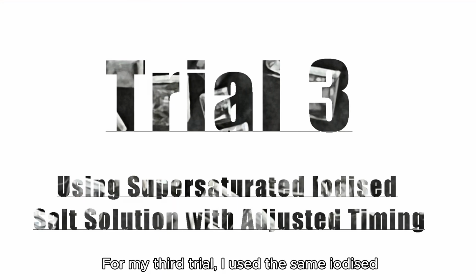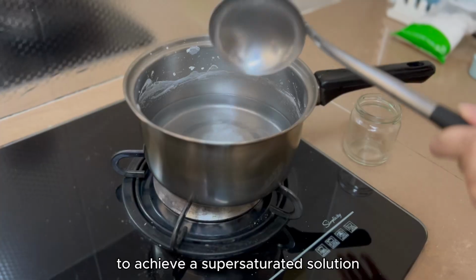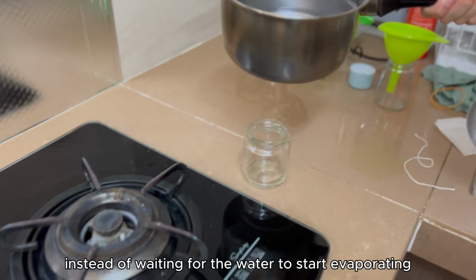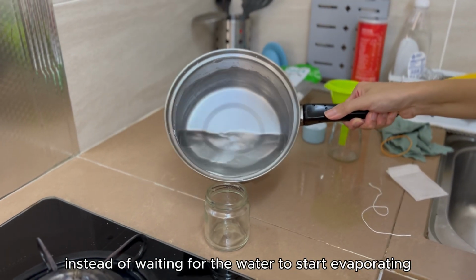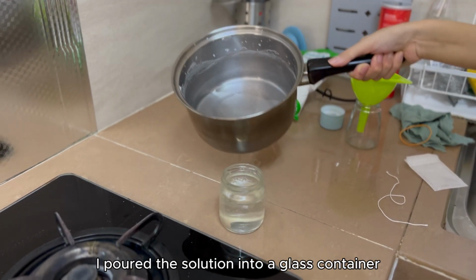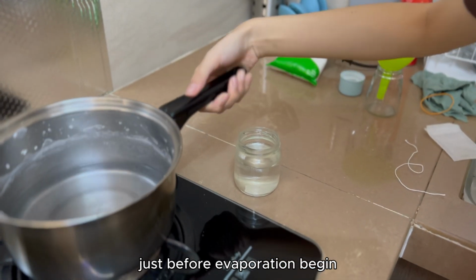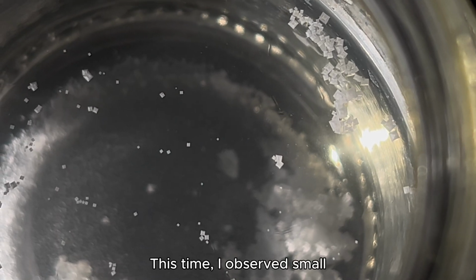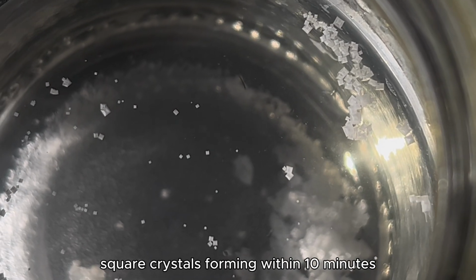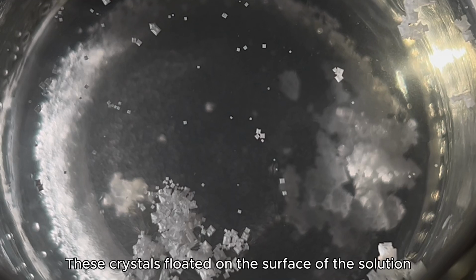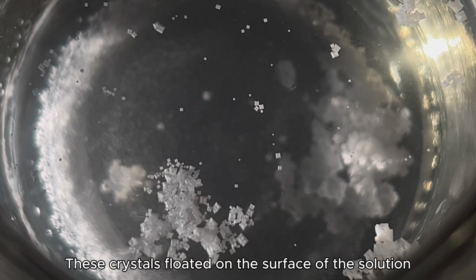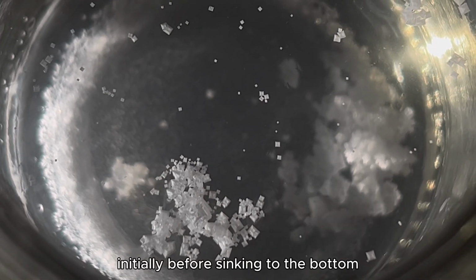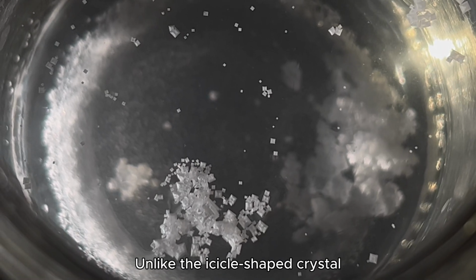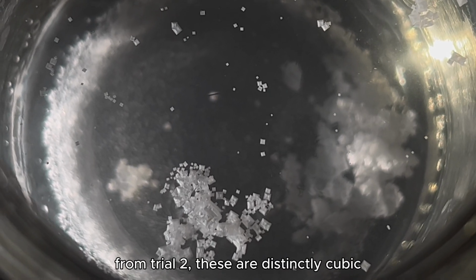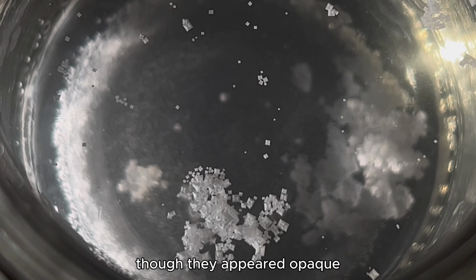For my third trial, I used the same iodized salt and heating process to achieve a supersaturated solution. However, instead of waiting for the water to start evaporating, I poured the solution into a glass container just before evaporation began. This time, I observed small square crystals forming within 10 minutes. These crystals floated on the surface of the solution initially before sinking to the bottom. Unlike the icicle-shaped crystals from trial 2, these were distinctly cubic, though they appeared opaque.